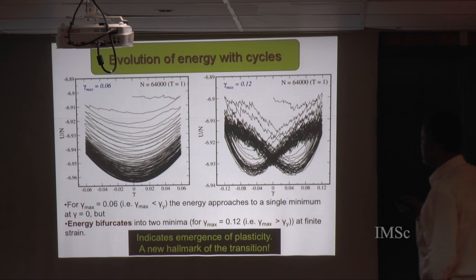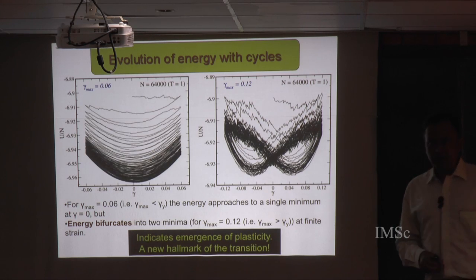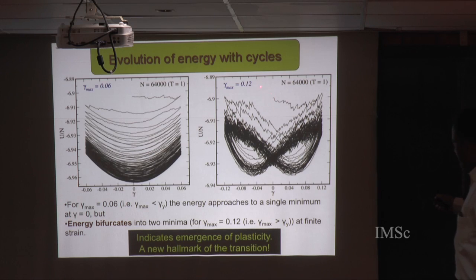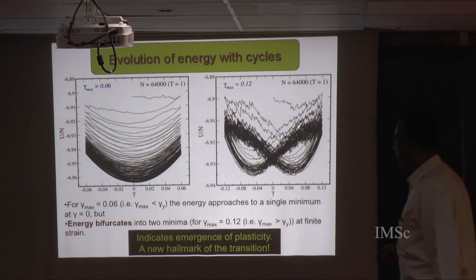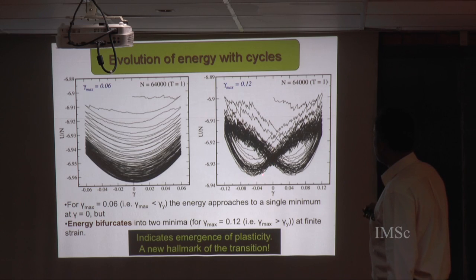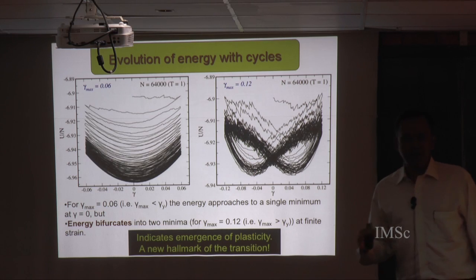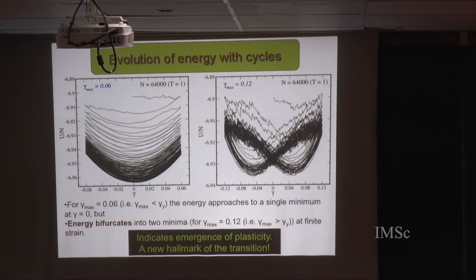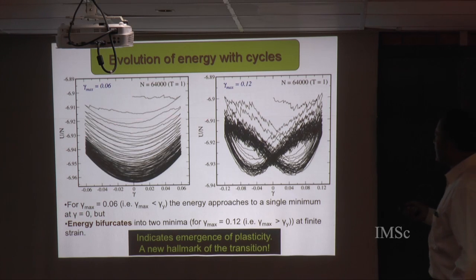If I now look at the same system at an amplitude above the yielding transition, I find a very different picture: the strain value at which energy is minimum bifurcates and is no longer at zero, and this bifurcation persists. The system finds the minimum energy at a finite strain value, which you can associate with the emergence of plasticity. This change in behavior is a new hallmark of this transition.